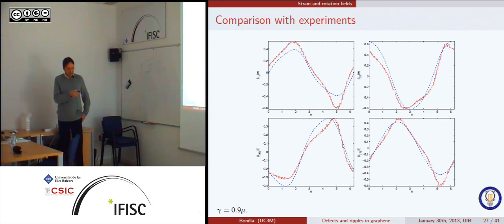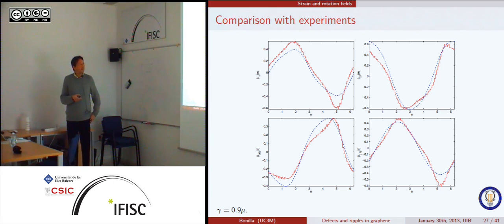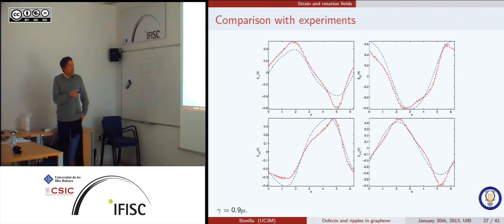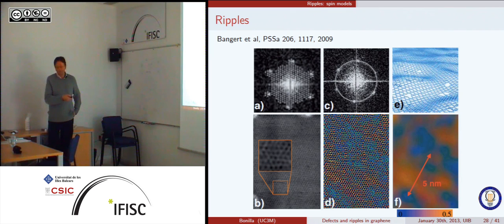This is just a comparison of, you just trace a circle about the dislocation of a certain radius. Here is 0.5 nanometers, I believe. And then you plot the different components of the strain and the rotation. So the red points are the experimental data. They are wiggly because, as you know, they are taken with points, so there are discreteness effects in this. And these are the formulas that we fitted. So we have a range of that material parameter gamma, which gives you a reasonable fit.